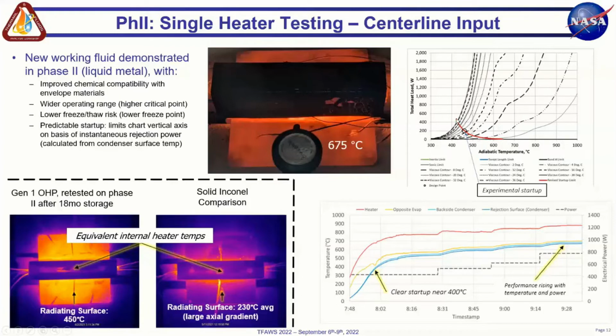Originally pioneered by Bruce Drolan, and he actually made an update to the startup limit to better match the startup experimental performance we're seeing with the liquid metal working fluid. Dashed in the boxes in the lower left, we took one of the phase 1 OHPs out of storage after 18 months, lit it back up, and it works nicely after 18 months of storage, actually with the working fluid frozen. And shown on the right, just an IR comparison, again showcasing qualitatively, to some degree, visually, the sort of isothermality that we can see with the OHP microchannels embedded in the envelope.